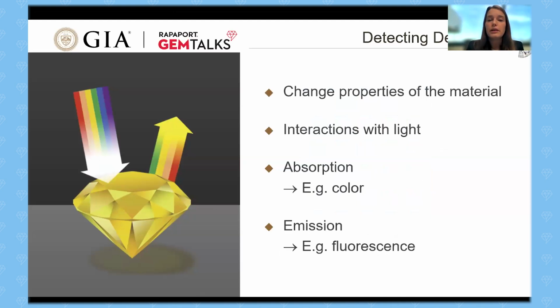So these impurities and atomic level defects are going to change the properties of the material. They will change the way that the diamond interacts with light. It can lead to absorption. If you have a sufficient amount of these defects or impurities, you will have a change in the color. And this is why, even though we call them defects or color centers, we have to keep in mind that these are not a bad thing. For instance, beautiful blue diamonds like the Hope Diamond are blue because of the presence of boron in the material. So these are not a negative thing at all. They affect the way that light is absorbed through the stone, and they also affect the emission of light.